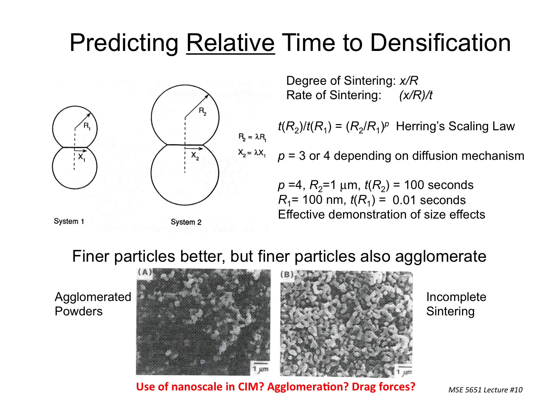And there's this, I just feel obligated to show it. There's a thing called Herring's scaling law. What Herring did was he looked at two characteristics of these two particles: the radius of the particle, R, and this variable x, which is the distance from the center of contact to the edge, meaning it starts to diffuse out and get away from this whole area. You look at that ratio of x to R, and it's supposed to give you some idea of the degree of sintering in the system.